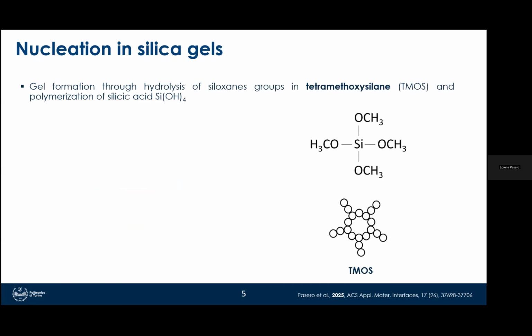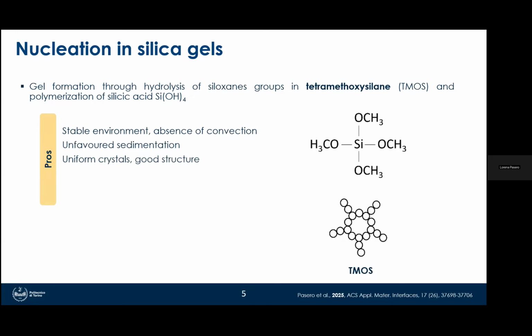These kinds of gels form through the hydrolysis of siloxane groups in tetramethoxysilane, which is used as a precursor of these gels, and the subsequent polymerization of silicic acid. And these gels, as I said, have a lot of advantages since they are able to create a stable environment where convection is reduced, but also they can disfavor sedimentation and provide very uniform crystals with a good structure, but also high mechanical properties, which makes these crystals very suitable for structural studies.